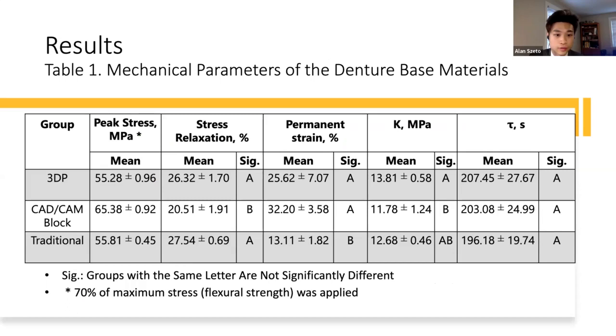Here is the data that we got. So here we got the mean for the peak stress relaxation percentage, permanent strain percentage, the capital K, which is the slope for the Voigt model, and tau, the retardation time, for each of the materials. If you look at the significance here, groups with the same letter are not significantly different from each other. So if they have different letters, that means they're significantly different from each other.